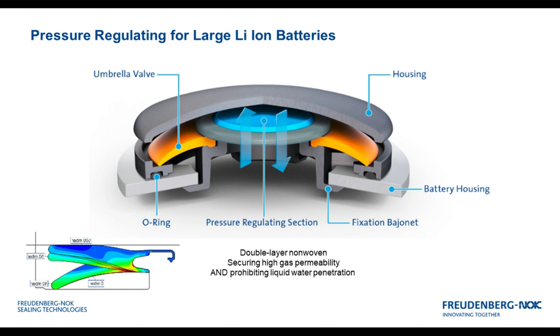This also will not allow any dirt, debris, or water to get into the housing. As well, the secondary function is accomplished by a silicone umbrella valve, pictured here in orange, that will open up and allow a large volume of gas to be released very quickly. And then, since it is an umbrella valve made of elastomer, after that large volume of gas has been released, it will come back down and seal and maintain that seal. And this unit here is rated to IP6K9K, so that way we can maintain the integrity of that battery housing with this unit.